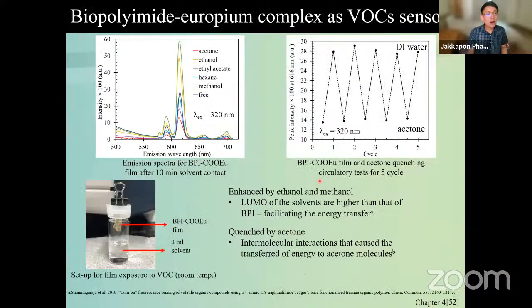Now, how I do it is I just clip the tapes here. This is the BPI Eu, and then I'm going to put the solvent here. All the solvents I use are acetone, ethanol, ethyl acetate, and so on, methanol, and then just water. You see that this VOC will just evaporate and touch the film. And then I'm going to put it under the UV.